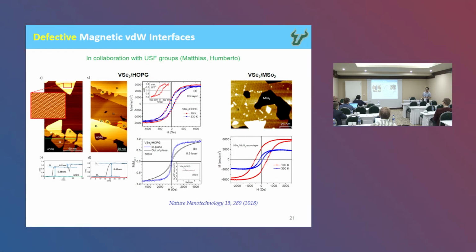In this case, as I mentioned before, there is interfacial coupling between the two layers, because MoS2 is known to have defect-induced magnetic ordering. So you have the spin induced by the defect from the MoS2 coupled with the spin from VSe2. And also, when you form the interface, you have charge transfer, which promotes or enhances the magnetic properties on both sides. That makes them couple very well, and gives rise to the enhanced magnetism in this particular case. Because of this, VSe2 on MoS2 turns out to be a very interesting system to explore the magnetic proximity effect and also exchange bias.